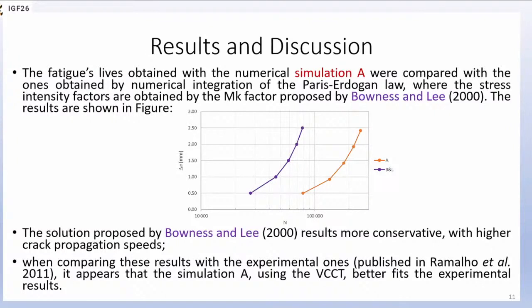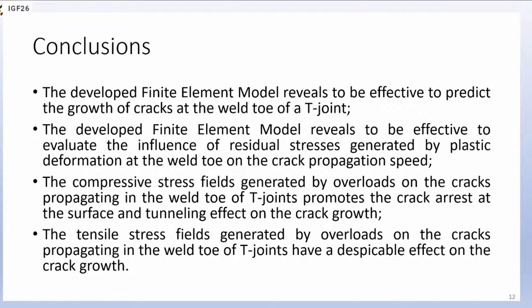The fatigue results obtained with numerical simulation A were compared with the ones obtained by numerical integration of the Paris-Erdogan law, where the stress intensity factors are obtained by the MK factor proposed by Bowness and Lee. The results are shown in the figure. The solution proposed by Bowness and Lee is more conservative, with higher crack propagation speed. When these results are compared with the experimental ones, it appears that simulation A using the VCCT better fits the experimental results.